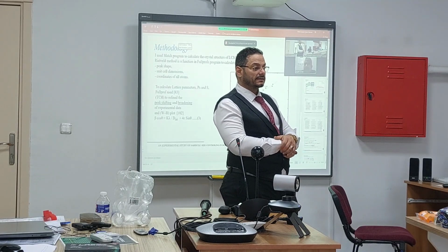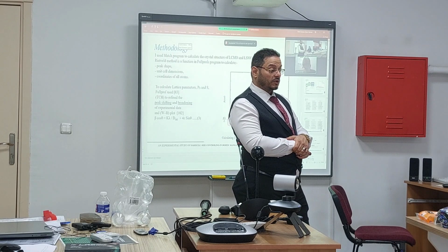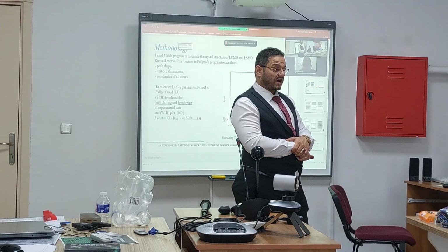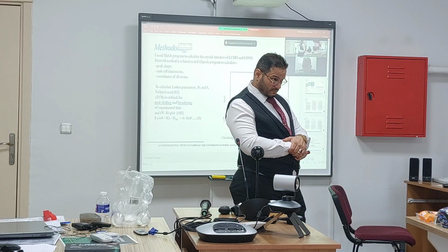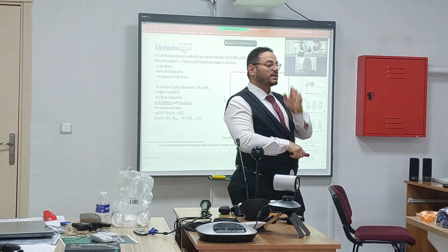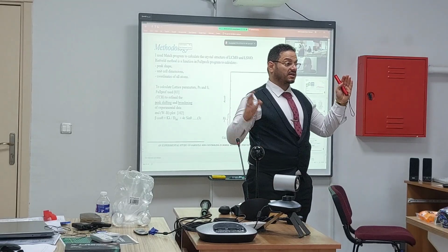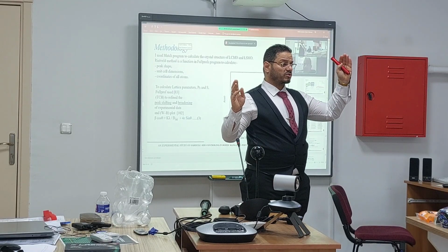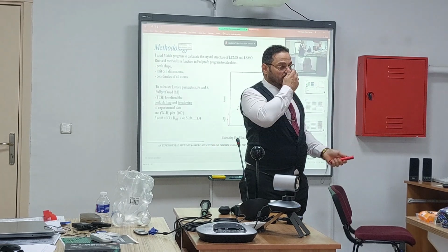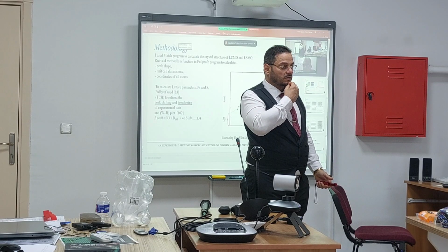You say sometimes particle size. How did you calculate the particle size by using XRD data? Particle size or crystalline size? Particle size and grain size are different. A particle will contain one or more grains. Most articles use the crystalline size. You can calculate the crystalline size by using XRD data.